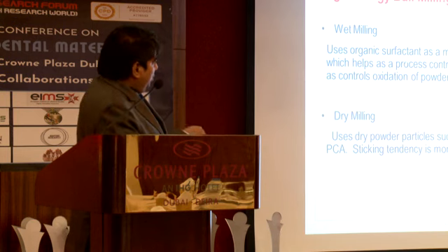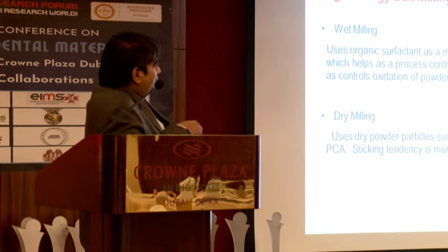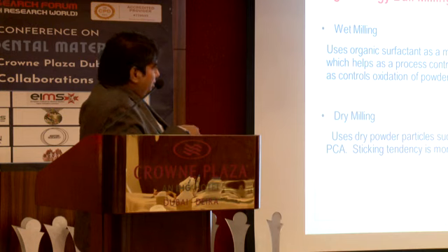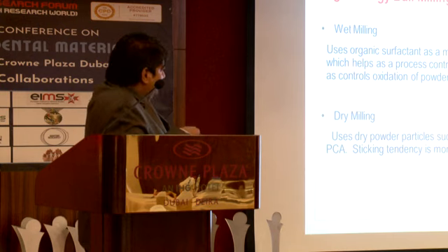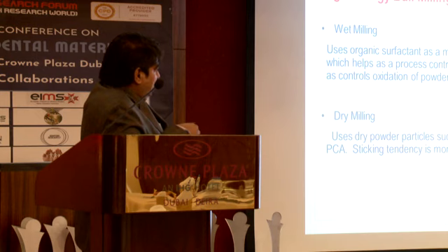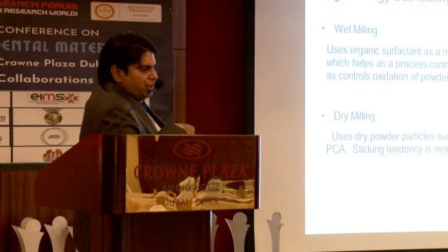So wet milling uses a PCA, which is a process control agent, toluene. It controls the milling process, one by increasing the efficiency of the process. Second thing is it also avoids oxidation. In the case of dry milling, you will be using stearic acid as a process control agent.